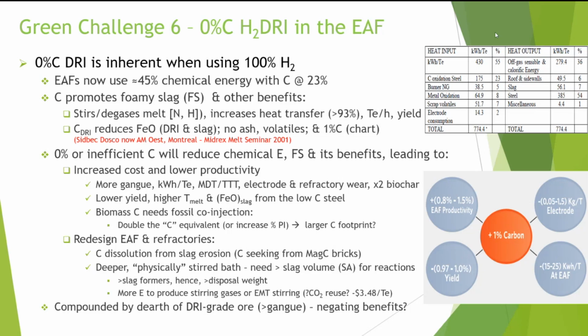If we have zero carbon in the DRI or inefficient carbon use, we're going to end up with increased cost and lower productivity because there's going to be more gangue in the system. We're going to have higher kilowatts, higher meltdown and tap times, higher refractory and electrode wear, lower yield, higher temperature and, with the lower carbons, more FeO in the slag. Biomass carbon needs fossil co-injection currently to operate correctly, although there is a new process that's supposed to be 98% efficient with injection, but the fineness of the carbon replacement is causing plugging in the equipment currently.